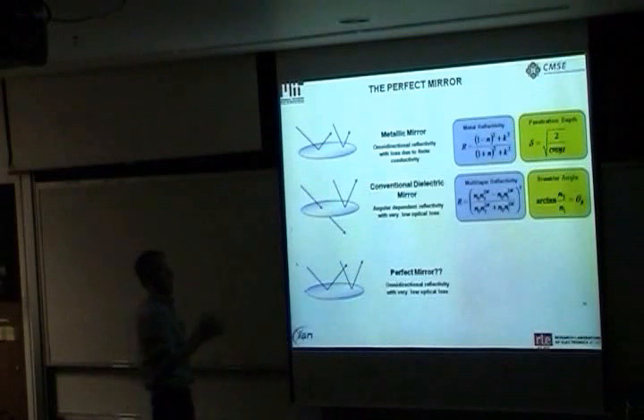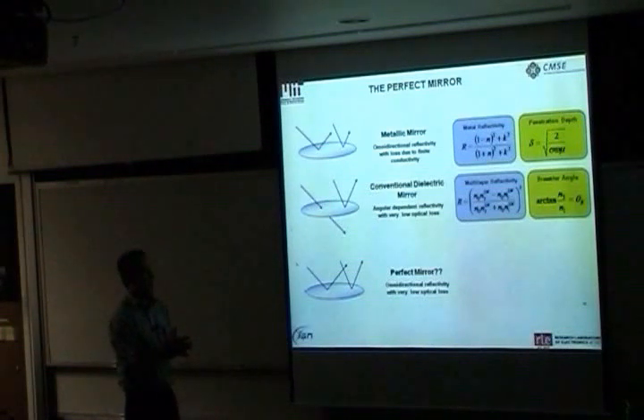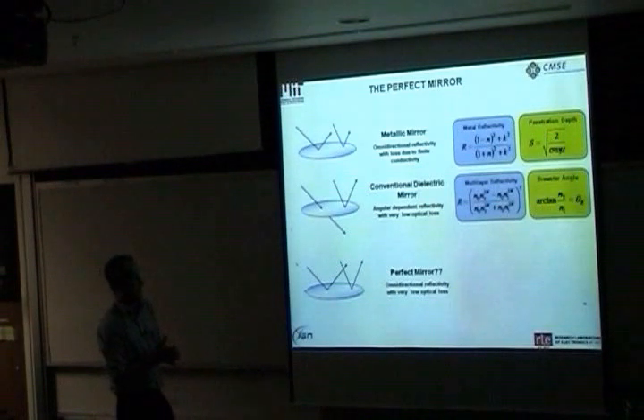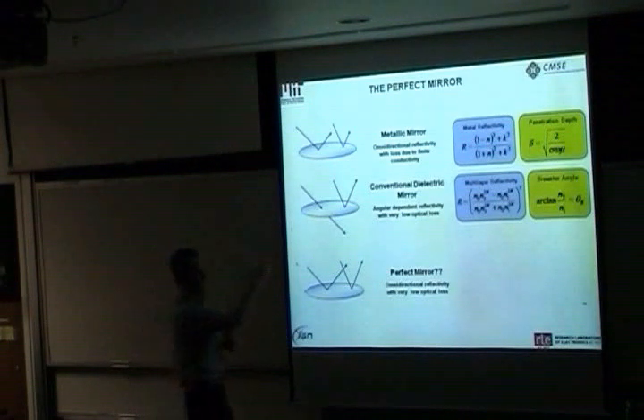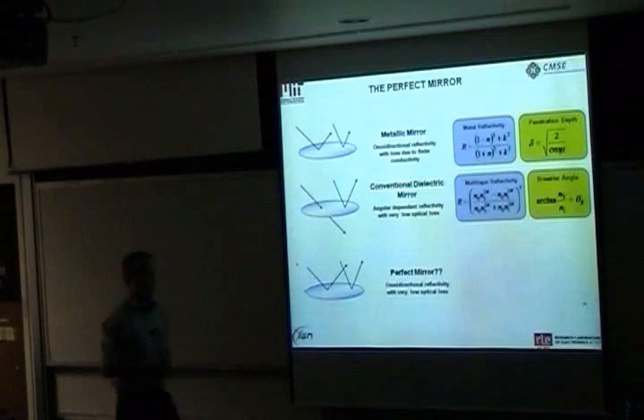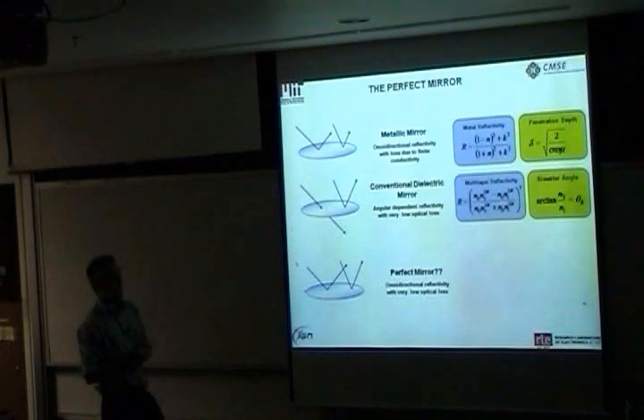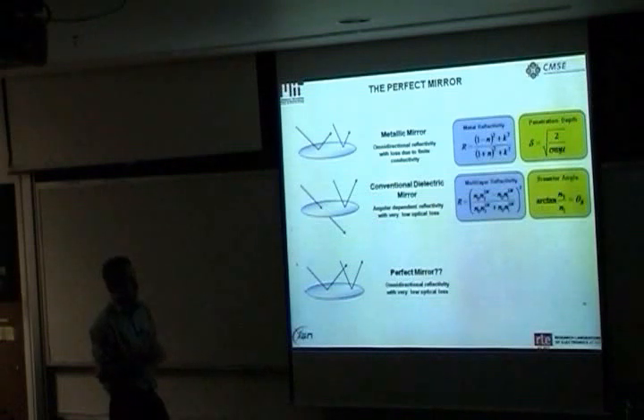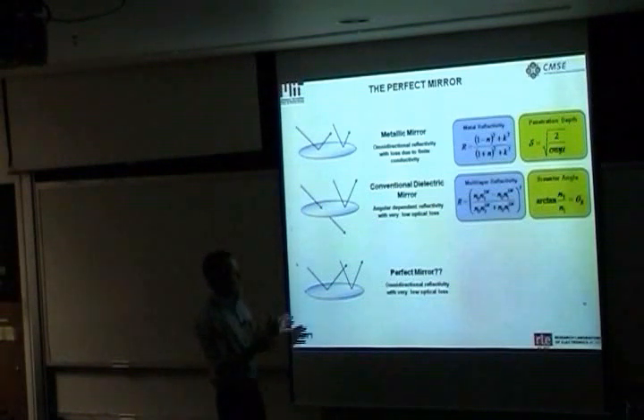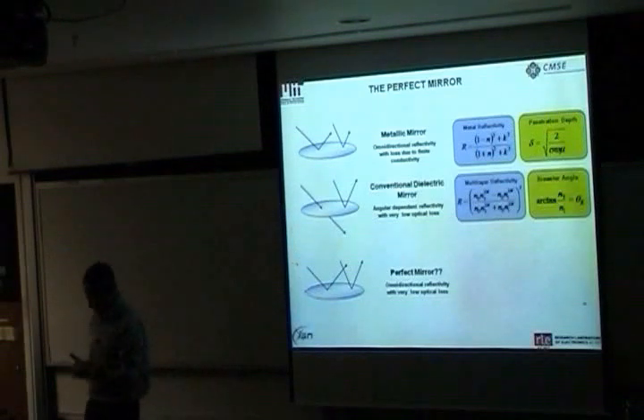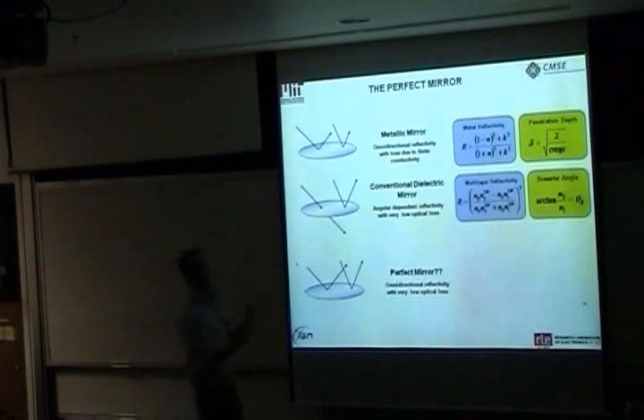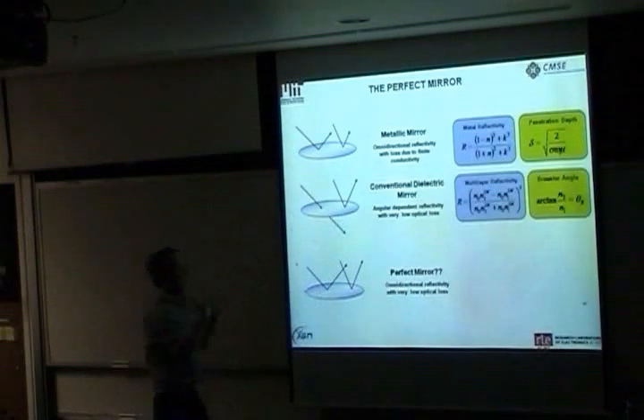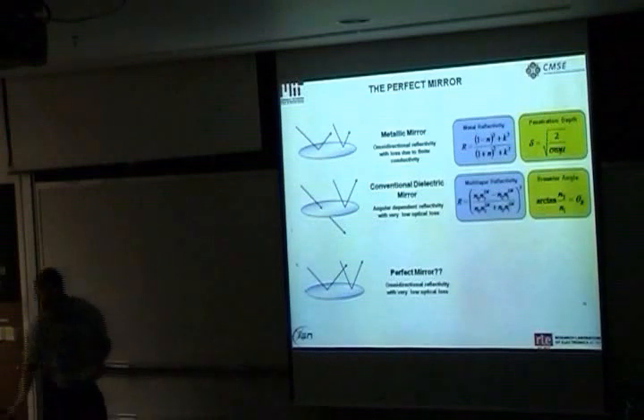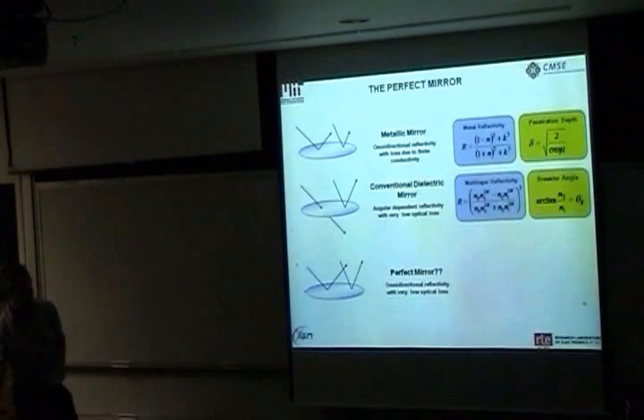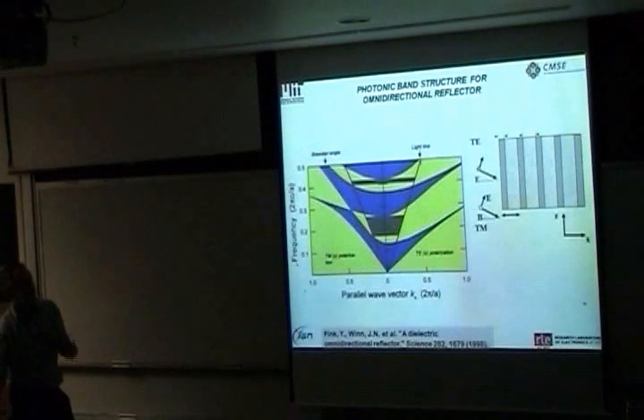So going back to the basics, there are a number of different types or classes of reflectors that we know of. One is based on just metals. And these tend to be omnidirectional in their reflection, but obviously have losses due to finite conductivity. Another type of reflector that is used in laser mirrors, for example, is that of a dielectric mirror. Here we're using one-dimensional periodic structures. And these tend to be very efficient at particular angles and angular ranges, but leak light, for example, at the Brewster angle. And so I was wondering if one could actually get the best of both worlds and design a mirror that would really bring us as close as possible to being the most efficient mirror possible, under a constraint that these mirrors had to be simply fabricated.